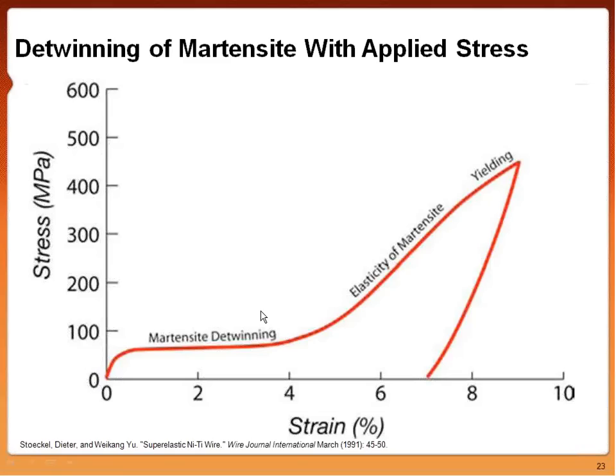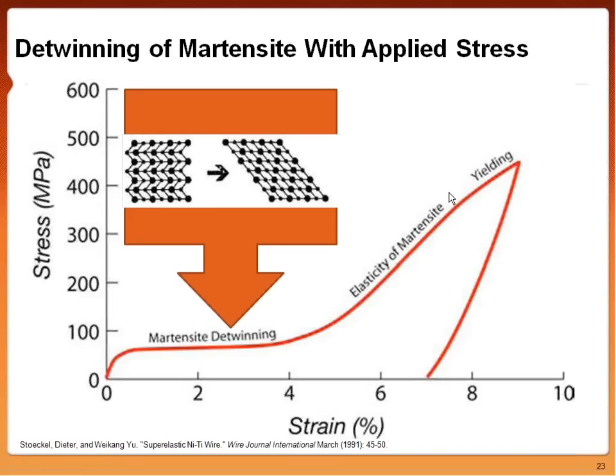So when we look at a typical stress-strain curve for martensite, we see that as soon as we have loading, we have a small elastic pulling of the martensite, and then we have detwinning. We reach this plateau where literally all the twins are taken from one state to the next lowest energy state to accommodate that stress. Once we've finished detwinning, we go to an elastic pulling of the martensite until final yielding. And this plays an important role as well with superelasticity.